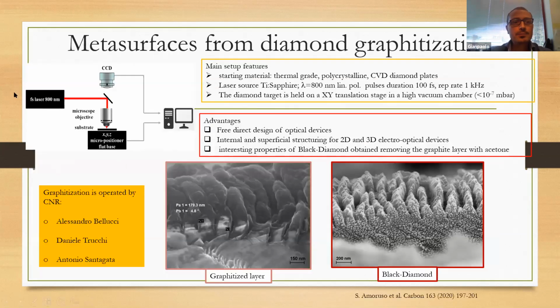Always with the femtosecond laser, with high energy, energetic pulses, we can fabricate metasurfaces, inducing a change into the phase of a diamond. We can turn it into graphite. What we have here is made in collaboration with the CNR group, so Alessandro Bellucci, Daniele Trucchi, and Antonio Santagata. We have written a paper on carbon, but this is just the beginning. These are our preliminary results.